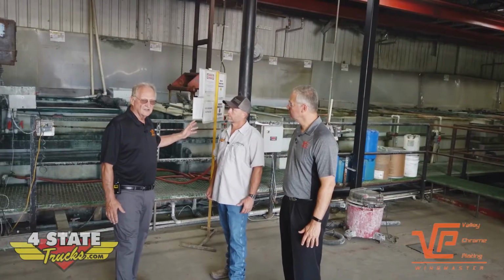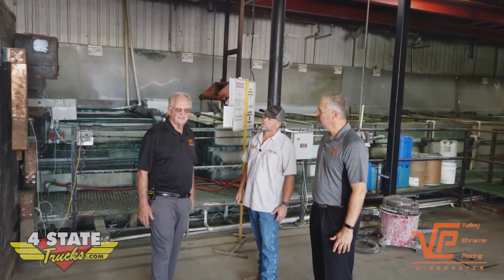Behind me you can see the chrome tank, and where it'll stay in the nickel for an hour, in the chrome it stays in for about 3 minutes. It puts on about 15 millionths of chrome, but it's like a lacquer over the nickel. We can't live without it, and the nickel is kind of yellow. The chrome makes it kind of a clearer coat.